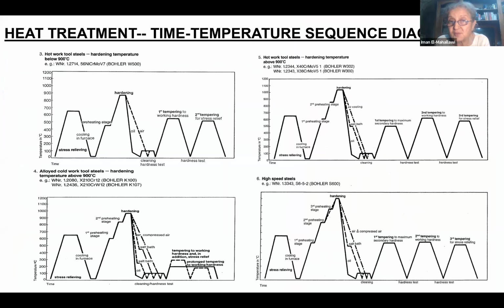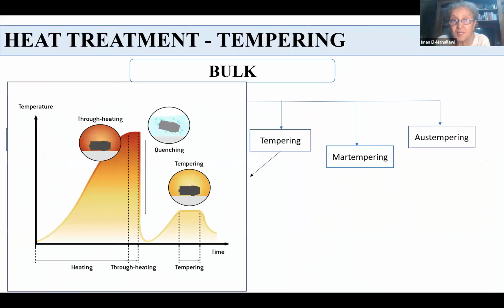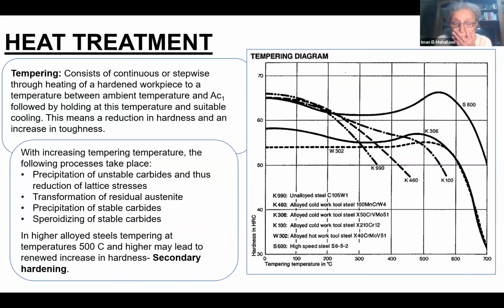Other examples for different alloys. Maybe martempering and austempering are not very well known, but they just mean that we temper in the range of martensite or we temper in the range of austenite to achieve the microstructure that we need. We also have not to forget that sometimes over tempering may produce some defects, because we have secondary carbide formation, which may harm the toughness of the material. So we should control not only the hardening stage, but also the tempering stage for achieving the required properties.